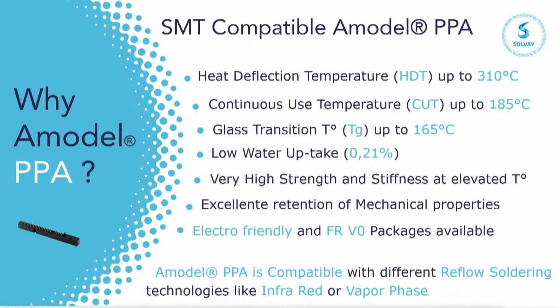Based on that, why A model PPA? First, A model PPA has a heat deflection temperature, HDT, up to 310 degrees C. The continuous use temperature is 185 degrees C. And the Tg, the glass transition temperature, goes up to 165 degrees C. Thanks to these characteristics, PPA is a material of choice for surface mount technology.